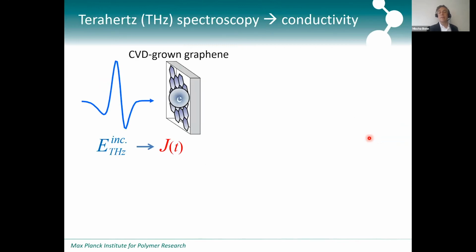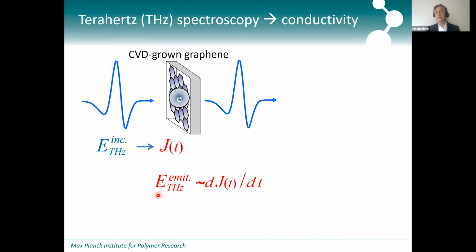So the underlying physical picture beneath this measurement is actually quite simple. The terahertz field accelerates these charge carriers, the electrons or the holes in the graphene, and thereby the field induces a current in the material. And that current, we know any current will emit or can emit a field, and the emitted terahertz field is proportional to the time derivative of that current.